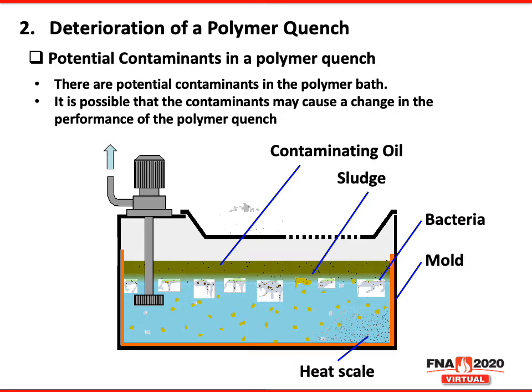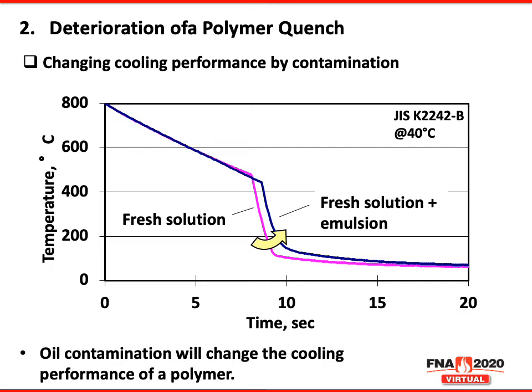Heat scale can be filtered. Mold, once that's in there, the system really should be dumped. Bacteria, you can use a biocide. Contaminating oil can be skimmed off and then slowly. So what does forming that oil and water emulsion do to your cooling speed? Instead of moving it to the left and making it quicker, it moves it to the right and makes it slower. Now, if the cooling speed is slower, your microstructure and your metallurgy may be affected.